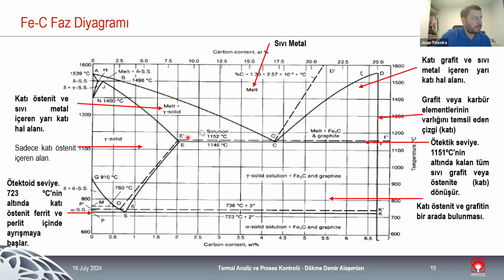And in this part, the solid part that we have is austenite. And on the other side, we have the same situation. We have a mix of liquid and solid, but the solid phase that we have is not austenite, it's graphite. And we are going to see that this is really important for a lot of different reasons. And we have the eutectic level around 1151, 1152. This is the separation between the semi-solid state to the 100% solid state. So everything lower than the eutectic point is solid.